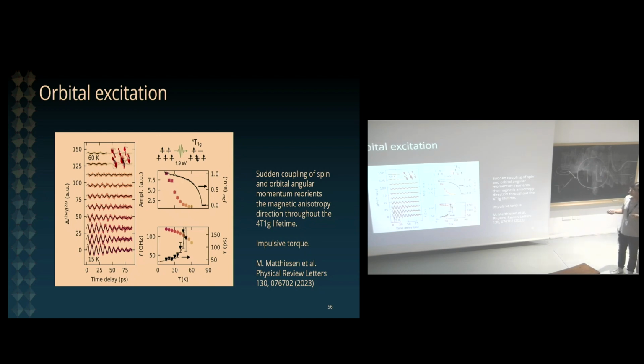So this system has some specific optically allowed transitions that reconfigure the orbital manifold. There is in particular this T1g transition, which brings about a reorganization of the electronic structure, which now gives an angular momentum to the orbital system. So if you excite this particular excitation, your system suddenly realizes that there is an angular momentum. This suddenly reorients the magnetic anisotropy of your system, and this can cause a spin precession. And that's what Matthias is measuring here. So suddenly at time zero, we are exciting the orbital degrees of freedom, and the system develops these nice coherent oscillations of the spins measured through second harmonic generation. Okay, and you can see the temperature dependence of both the frequency and the amplitude, which are quite peculiar.